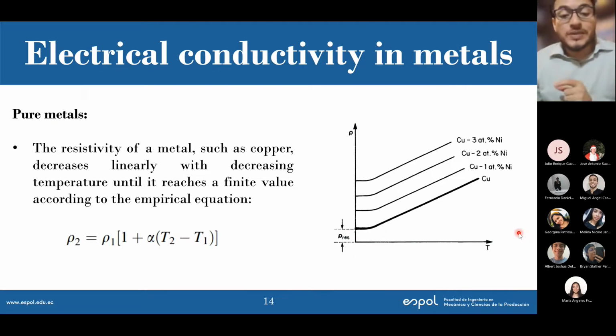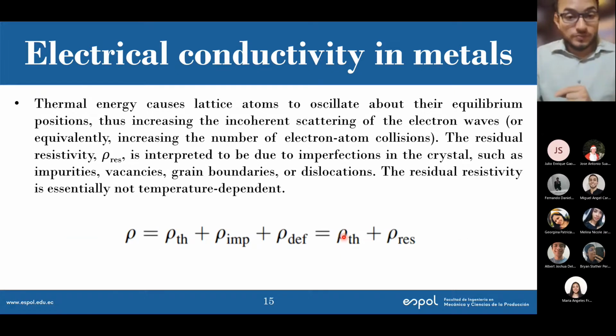But there will always be this residual resistivity term, and that term is quite important. The residual resistivity is basically the accumulation of different resistivities due to imperfections in the crystals. That is, for example, impurities and defects, defects being vacancies, boundaries, dislocations, everything else. There is a term that is resistivity because of thermal energy, so this term is temperature dependent, and the residual resistivity is not temperature dependent.